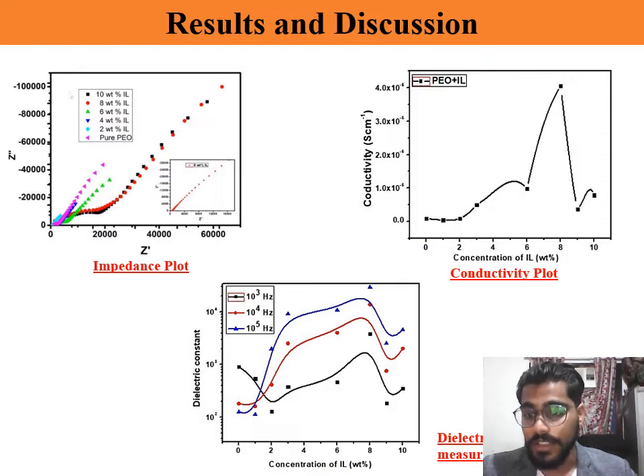Next, we have the conductivity measurement. The EIS spectrum of pure and ionic liquid doped PEO are analyzed as shown by the figure. By analyzing the EIS spectrum, the ionic conductivity of pure and ionic liquid doped PEO are calculated using the formula of conductivity given by 1 upon Rb times L upon A, as we are very much familiar with this formula. This conductivity value is quite comparable to that reported by other researchers, where they got the value of 10 to the power minus 6 Siemens per centimeter.